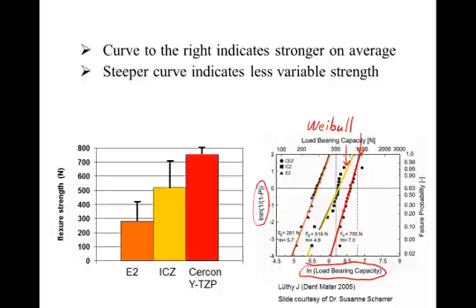The slope of the line is called the Weibull modulus, and it's often represented by m. Sometimes it's also represented by beta. And the slope in the case of the red line is 7. In the case of the yellow line it is lower, 4.6, indicating more variability. Now, how that relates to a bar chart that you may be more used to reading, you can look at the standard deviation. The standard deviation on the red group is very small. So a small standard deviation bar is similar to having a steep line on a Weibull chart, and the standard deviation for the yellow group is quite large, and so a large standard deviation or large error bars is the same as having a less steep slope on the Weibull graph.